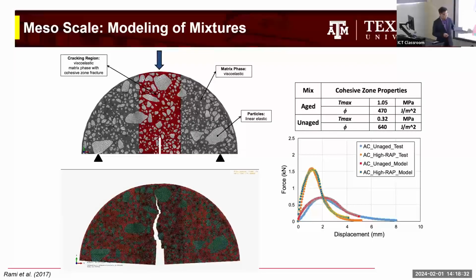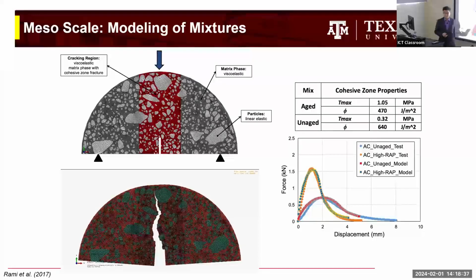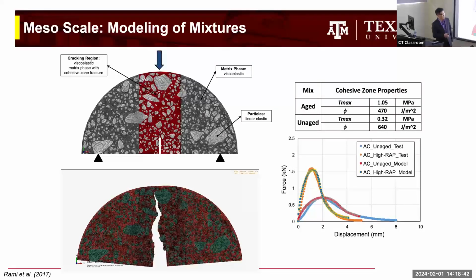And then as you can see, we can simulate a crack development through the sample. I think it's kind of a realistic fracture. If you do testing, you can probably see it this way too. And then you see the comparison between the aged group versus the unaged group, high RAP versus unaged, and the model can capture the damage process, the entire process, like the testing we do in the laboratory. So modeling of mixture works.